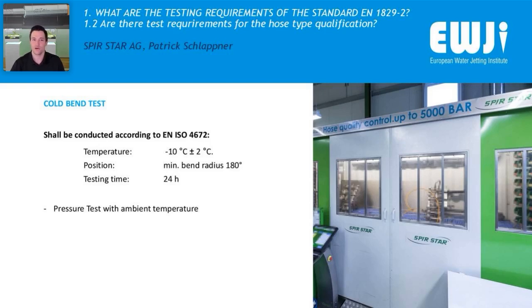After the 24 hours, we do another pressure test, but in this case in the normal atmosphere with an ambient temperature. If there's no leakage, the test is confirmed.